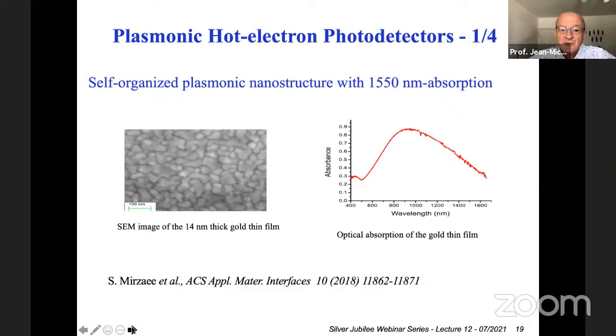And during the deposition, the gold, which doesn't wet very well the ITO surface, agglomerates into some clusters, like you can see on the figure. It's a scanning electron microscopy image in which the horizontal green bar is 100 nanometers long. So you see we have little clusters which are in the range of 50 to 100 nanometers. These things are not regularly organized, which means that they can have their own plasmon resonances, and they can sustain coupled plasmon resonances.